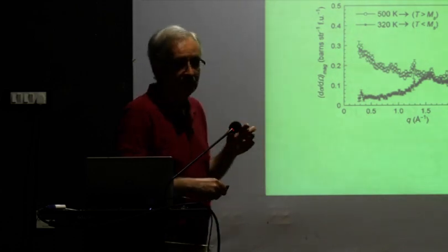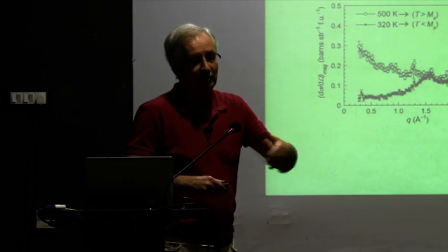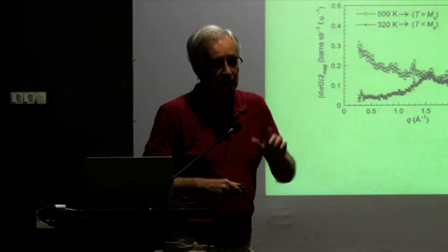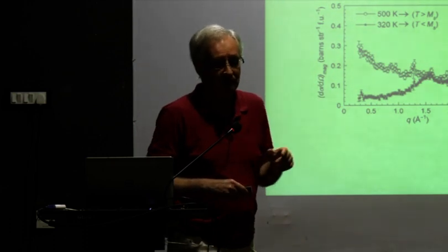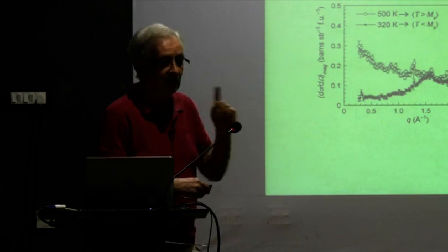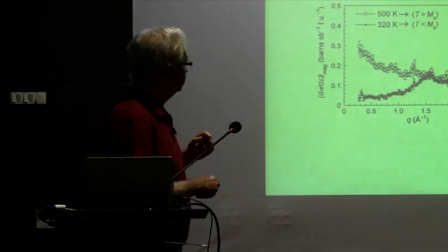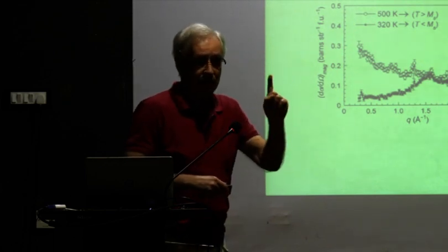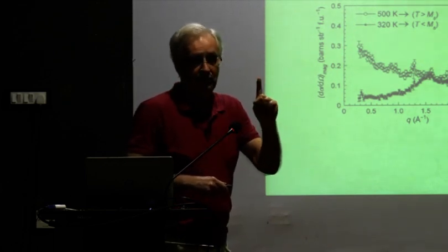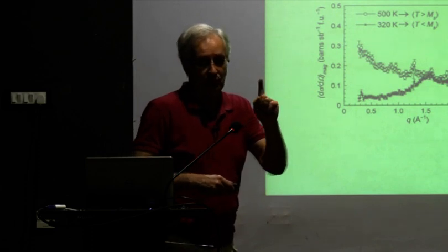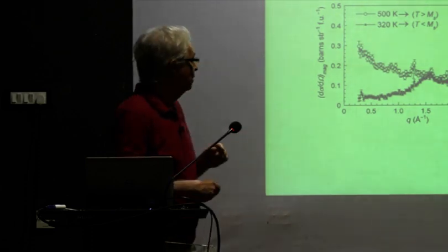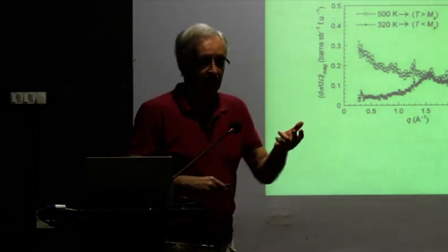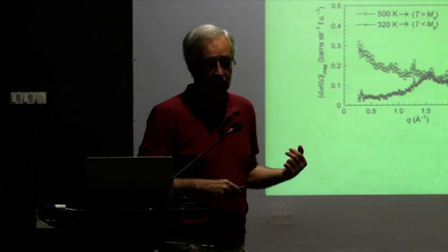It is so broad that it is on the order of the nearest or next-nearest neighbors. But the only thing that we can say is that, yes, we have ferromagnetic correlations at high temperature, way above the Curie temperature. When it comes down to the Curie temperature, there is a tendency to order ferromagnetically, but it does not. It undergoes a martensitic transition.